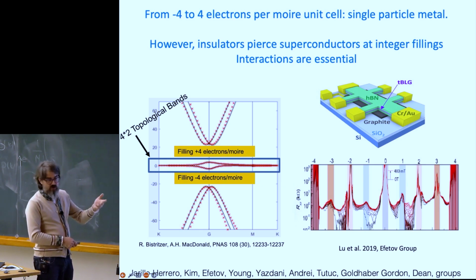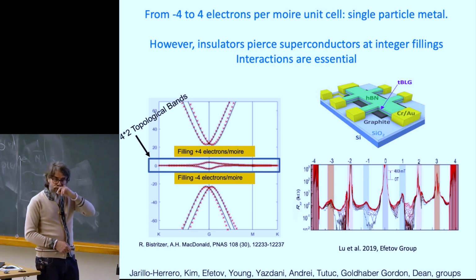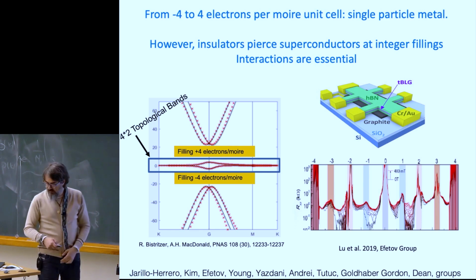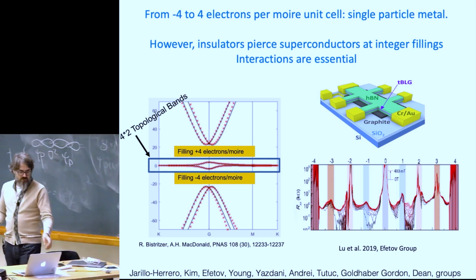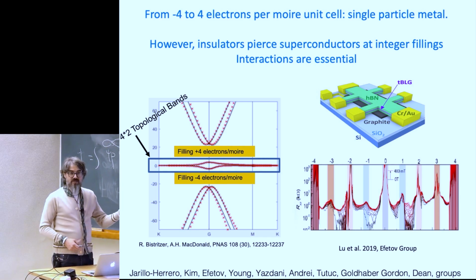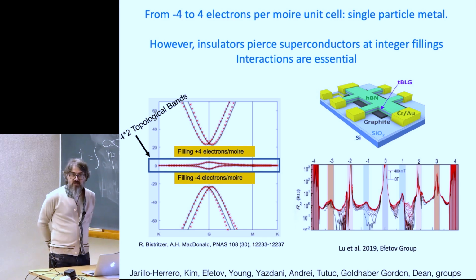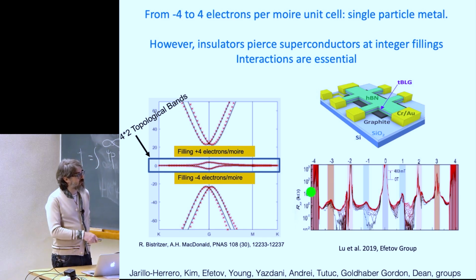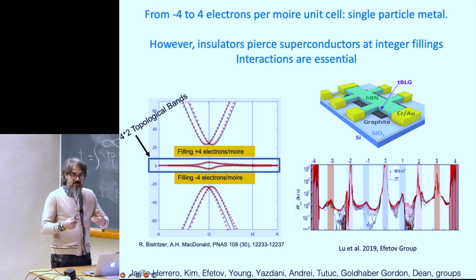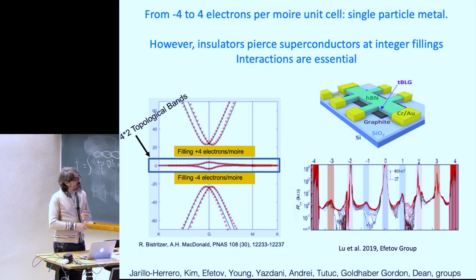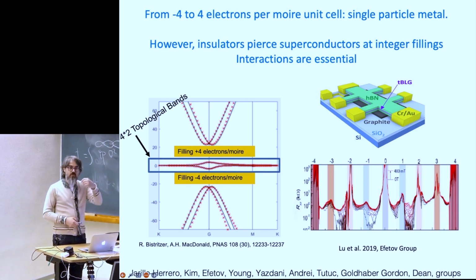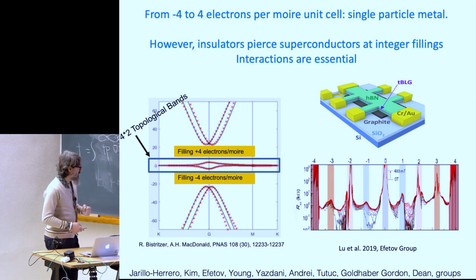Charge neutrality, the reason why we want to count it like this, charge neutrality, i.e. Fermi level 0, we're going to say it's 0 electrons. It's just a way of counting it. Now, why is this good for people that don't do condensed matter? How is this better than material chemistry? Well, here, in order to put electrons from here to here, I need 8 electrons. So to populate these flat bands, I can put minus 3, minus 2, minus 1. Okay, now that's electrons per Moire unit cell. The Moire unit cell contains 10,000 carbon atoms, 10,000 original unit cells. So really, this is a very small doping at the original graphene lattice.